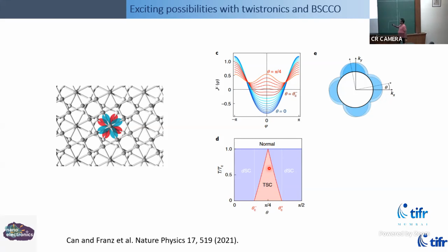This red region tells you how much twisting you can tolerate and still be able to get this topological superconductivity. So this was quite a remarkable prediction, and there was also debate whether all aspects of it are correct. But since this was an interesting enough prediction, we leapt into it, and that was the genesis of our work on twisted junctions of BSCCO, which is twisting layers of BSCCO by an arbitrary angle and then trying to measure the Josephson junction that is formed.